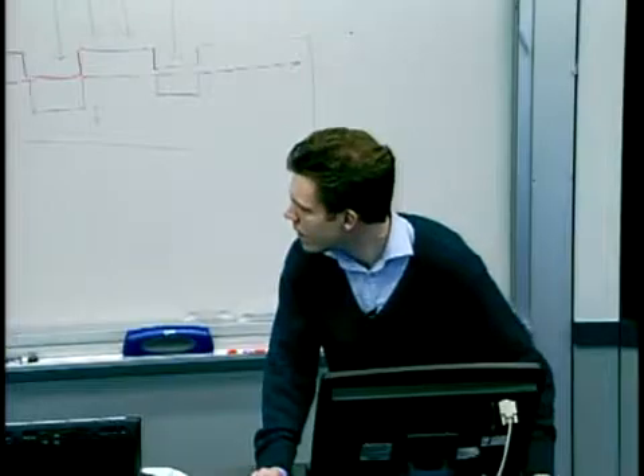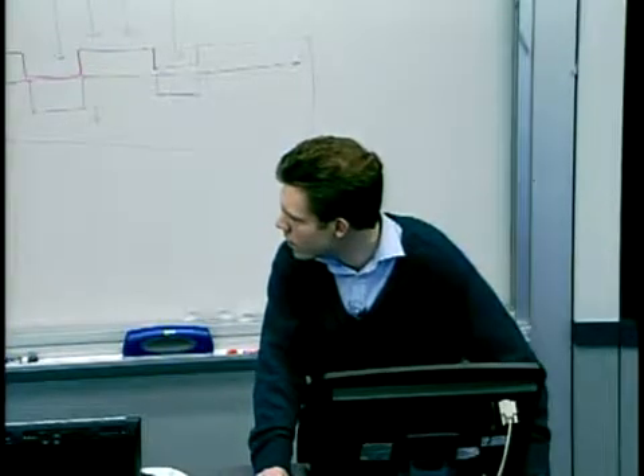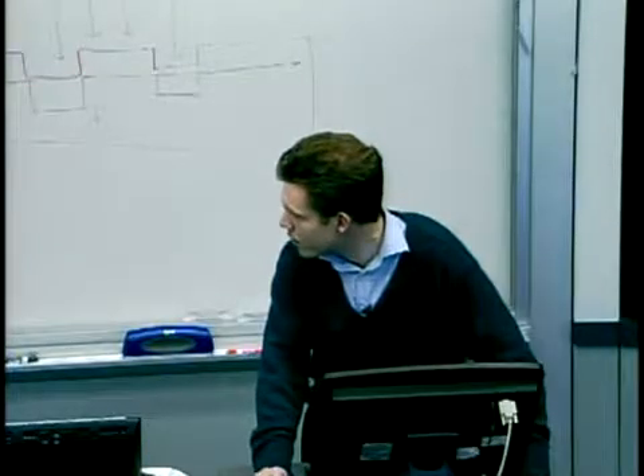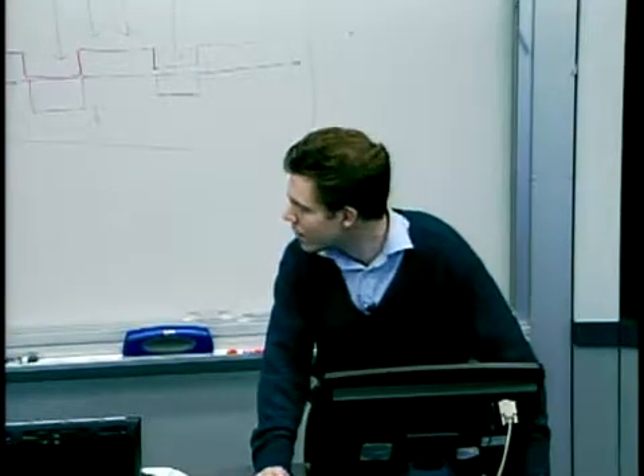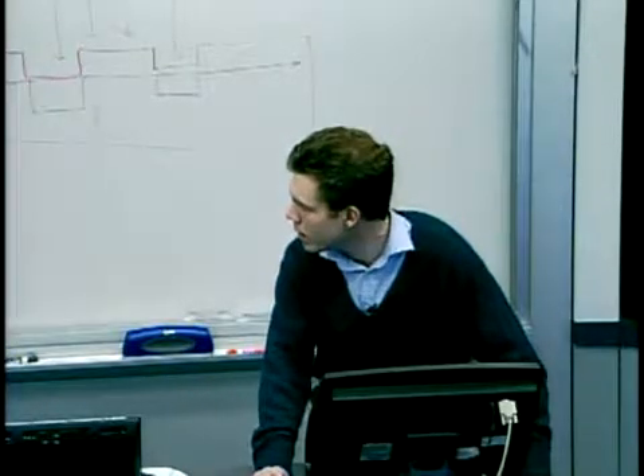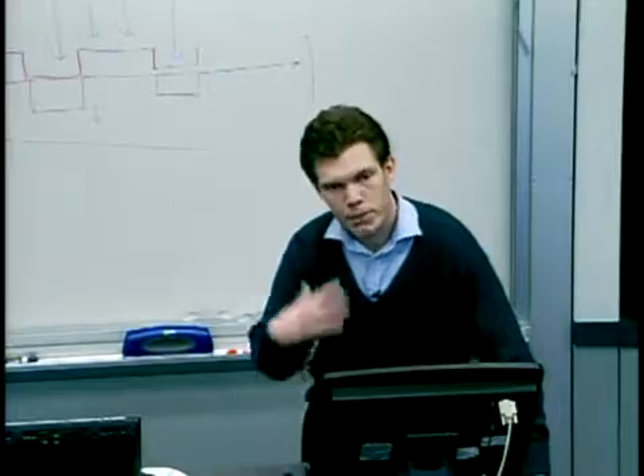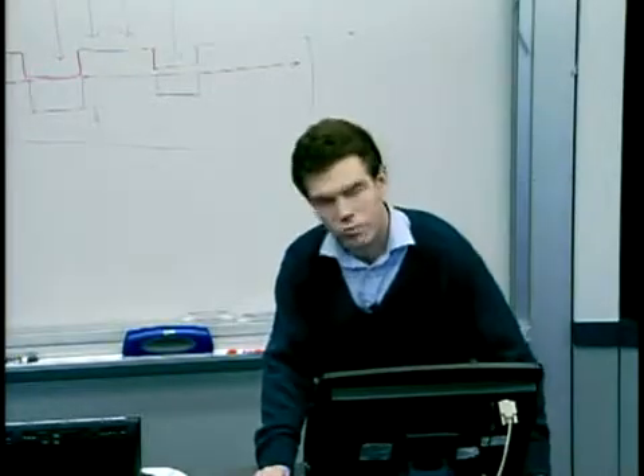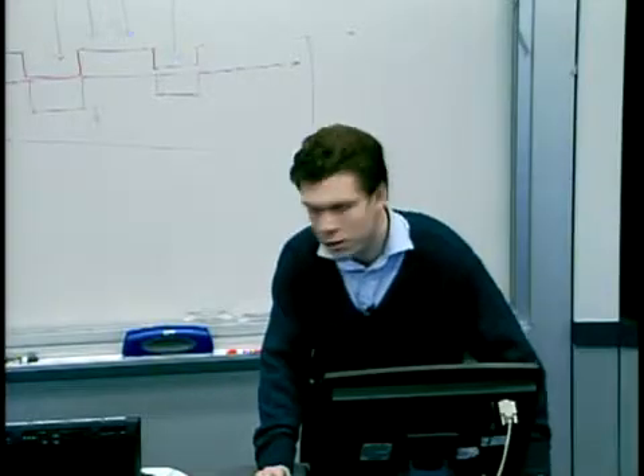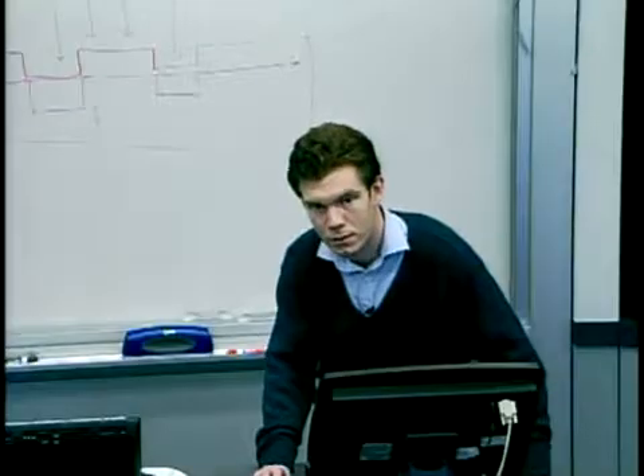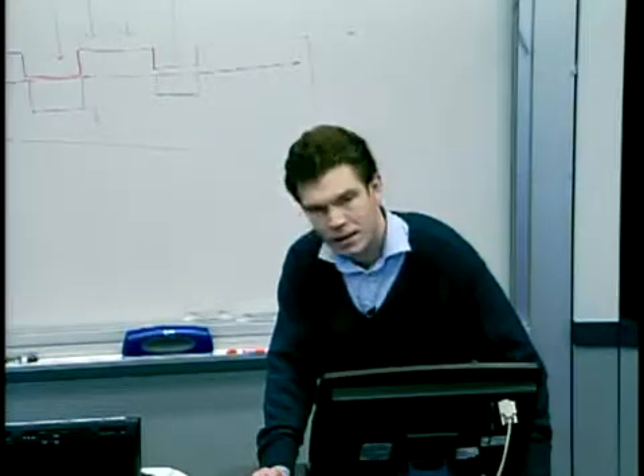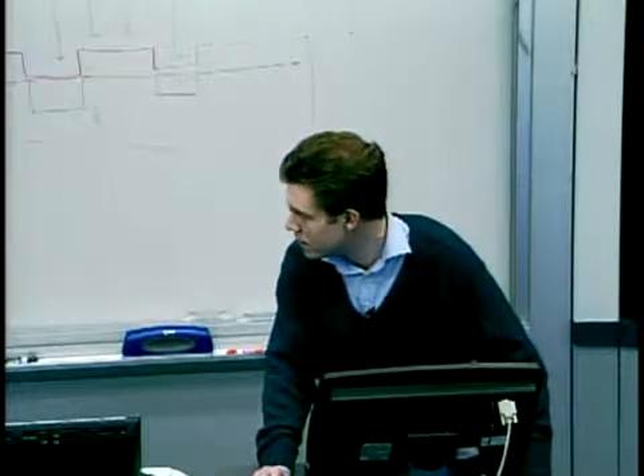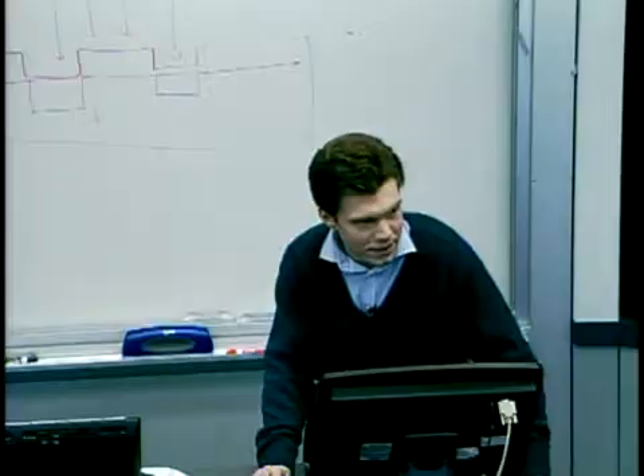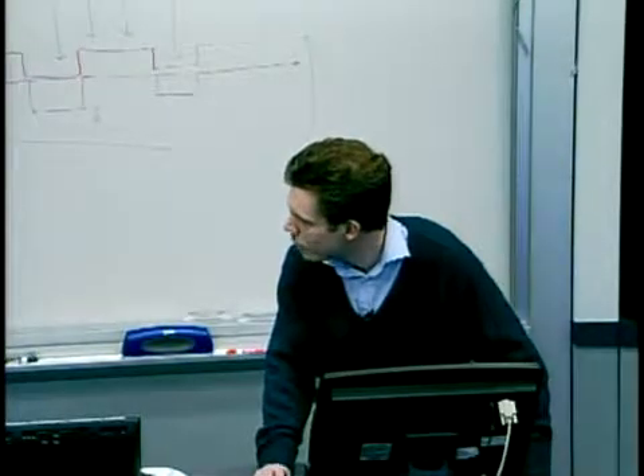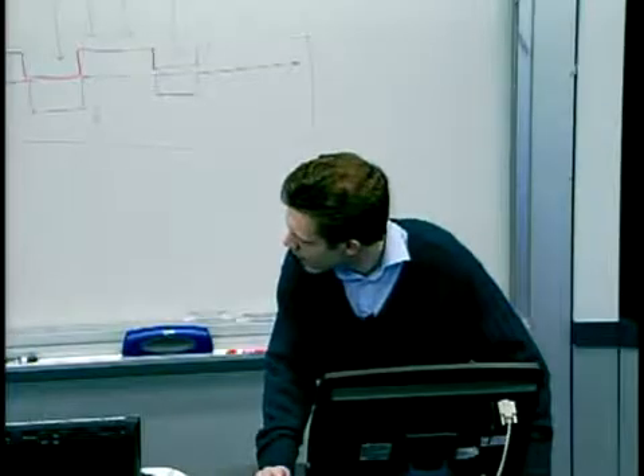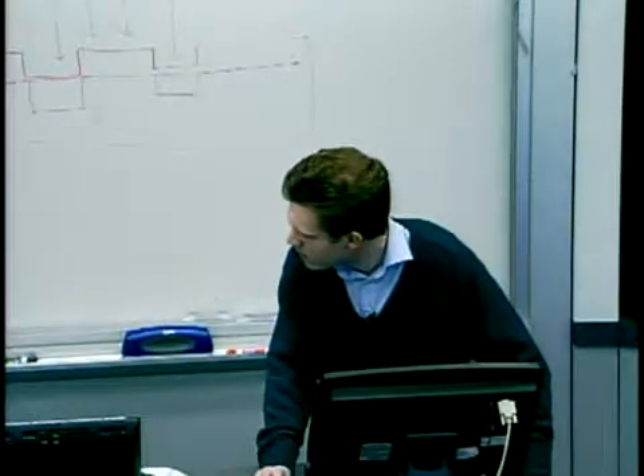This shows one particular substrate that we emboss. This is a square of PMMA, which is acrylic, which is about 100 millimeters square. We embossed with a wafer that had been uniformly patterned with some silicon posts, roughly 100 microns in diameter, and we just use this as a probe to look at our embossing machine and see how uniform a pattern could be produced. Now, aside from the fact that huge chunks of the silicon wafer broke off during demolding, and that's a good illustration of some of the problems that we face, we were able to look at the topography of the pattern at different locations on the wafer.